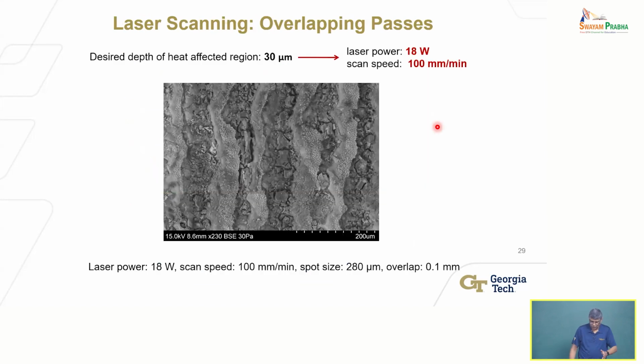Okay, now this is showing you what the surface looks like for one condition at 18 watts. In this case, the desired depth. And here we are overlapping passes. So you have to design this. You have to design overlapping passes to ensure that the entire surface area where you're going to remove material is thermally cracked, unless you have a laser with a large spot size and enough energy density to do it in one pass, which we didn't. So because of that, we need to scan, right? So this is what has been done.